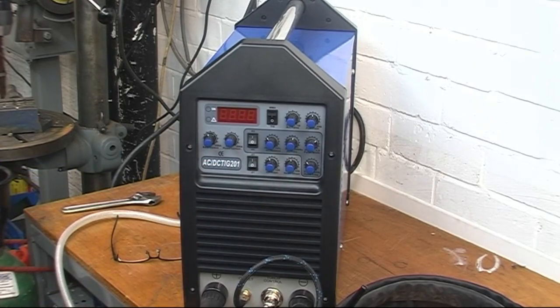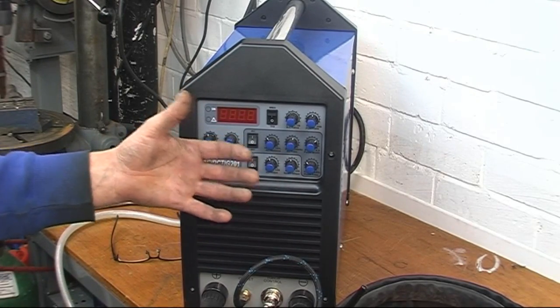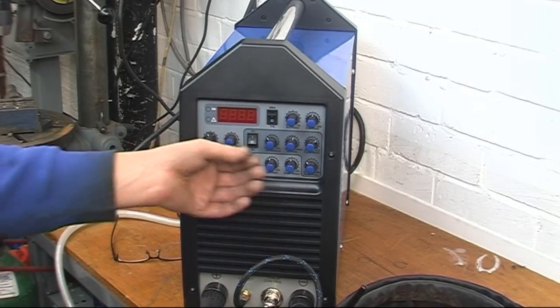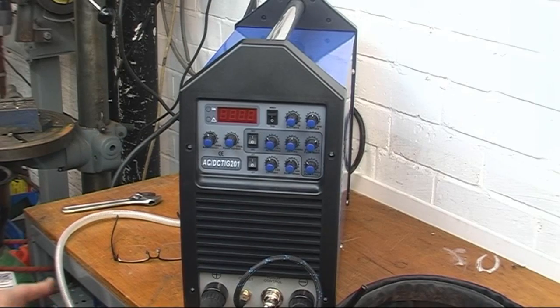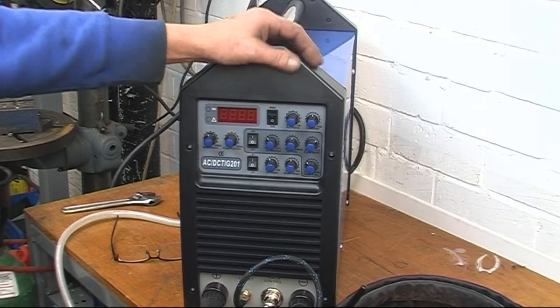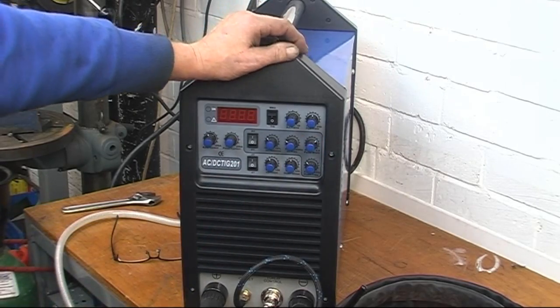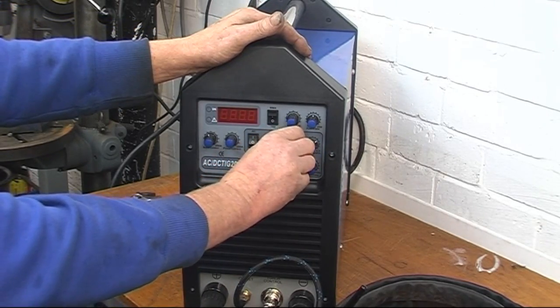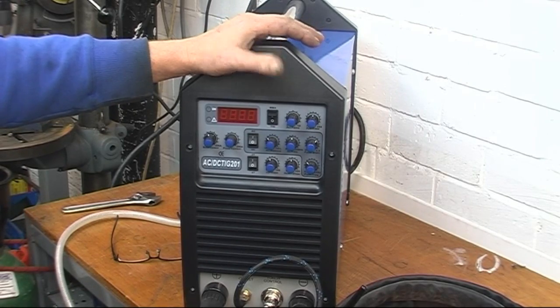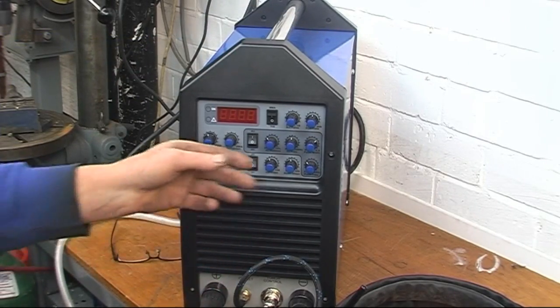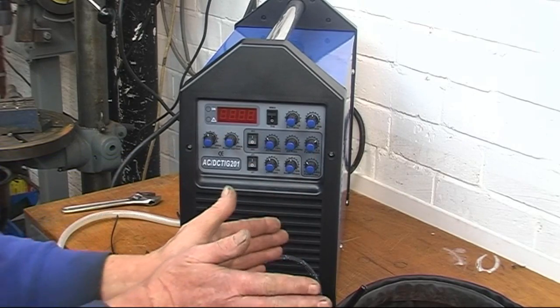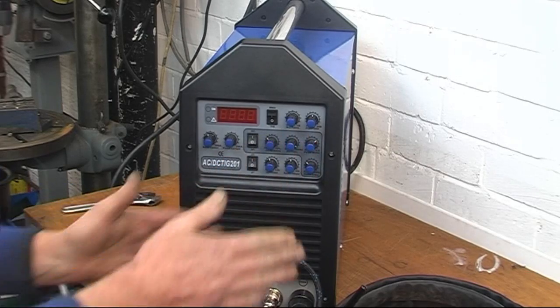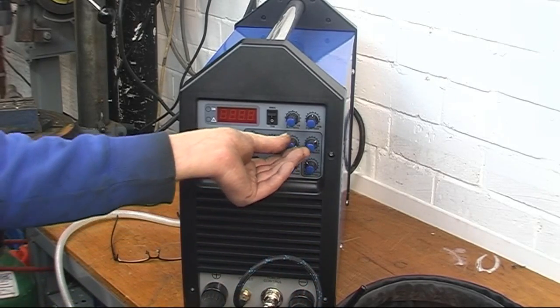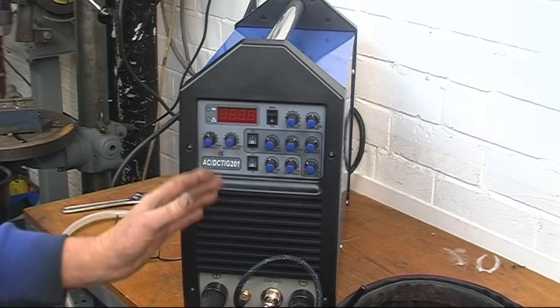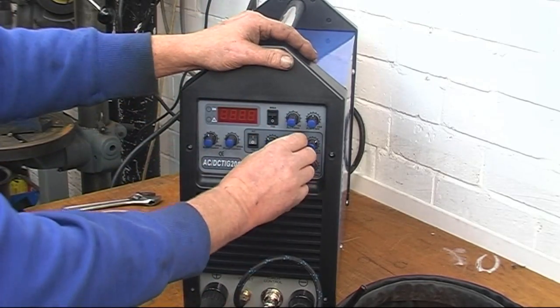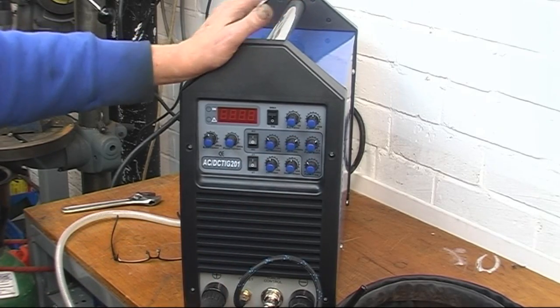This one here, AC frequency, that's how fast it goes, how the alternating current works, positive, negative, positive, negative. On old-fashioned transformer welders you are stuck at 60 Hz. With this one it goes from 50 all the way up to 250. What this does, it has the effect of tightening up the arc. If you set the arc like a flame, if you have it down at 50 you've got a wide bushy flame. If you turn it all the way up, the flame tightens to a pencil point. You can hear it as it's welding, as you wind it up, it starts to screech higher and higher and higher. Normally aluminium, but 120 is the sweet spot for welding aluminium.